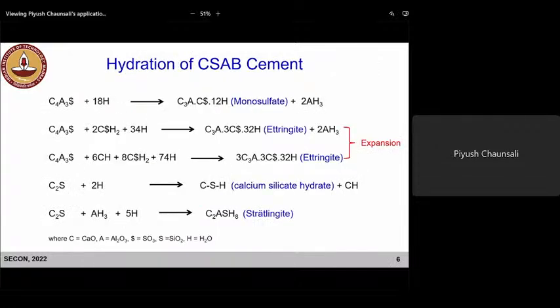So hydration of CSAB cement is different than what we see in Portland cement. So this C4A3S, which is calcium sulfoaluminate cement, can just hydrate in presence of water and form monosulfate. Monosulfate is the phase we also see in Portland cement hydration, when later on ettringite converts to monosulfate when the gypsum depletes, right? Apart from monosulfate, you have formation of aluminum hydroxide. This is the reaction which takes place just in presence of water. But since we have gypsum in the system, again we are using the cement chemistry shorthand notations. So please refer to these for more clarity.